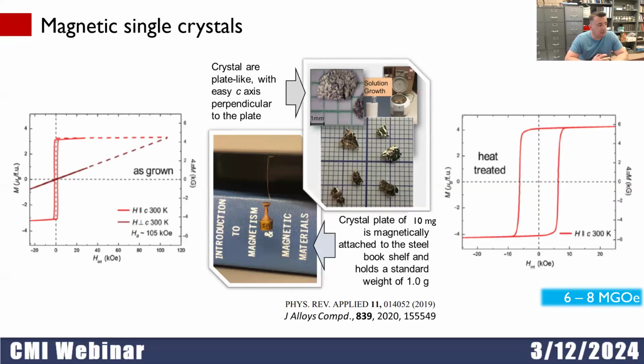Yeah, we worked with Samarium Cobalt 5, but Samarium Cobalt 5 is absolutely horrible from the perspective of practicality until you put a little bit of copper in it. And when you put copper in it, you will see that everything magnetically changes very much because extrinsic magnetic properties develop even in nominal single crystals. For example, here we grew single crystals and we heat treated them. Those single crystals transformed themselves easily into the permanent magnets with perfectly square hysteresis loops.